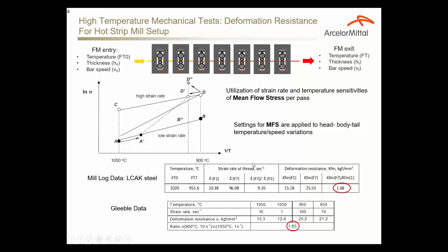The first step was to make sure that the Gleeble data and the numbers that we obtained during the test are translatable into mill language. The mill wants not the stresses per each stand. They want the ratio of the deformation resistance in the last stand to the first stand. That is linear. This linear relationship allows them to set up the level 2 model and then adjust it for the rolling. So we ran the trial test, low carbon aluminum killed steel, and we found out, well, we're pretty close.